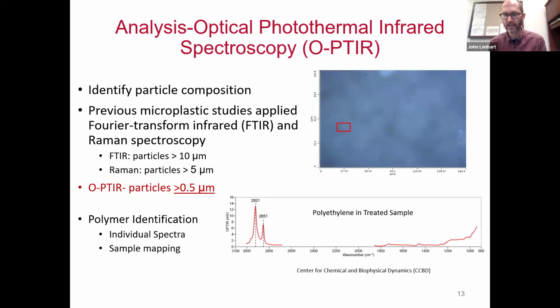The other technique that we're using allows us to identify the actual polymer type, and this is called optical photothermal infrared spectroscopy. The advantage of this is that it allows us to identify smaller size plastics than other techniques. Other techniques that people have used are infrared, FTIR, and Raman spectroscopy, and those are nominally good for particles greater than 10 microns or 5 microns. The technique that we're using allows us to identify plastic types for particles greater than 500 nanometers. So we're looking at nanoparticles specifically.